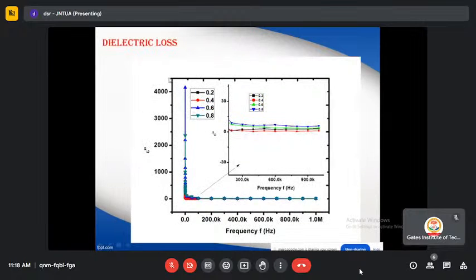Similarly, this is the plot between epsilon double dash and the frequency. The epsilon double dash values are also found to be 4575 and 2657 for the same compositions. In general, at smaller frequencies the grain boundaries become more active, whereas grains are more active at larger frequencies. This has been reported in literature. From this, we can say that grains exhibit a low resistivity, whereas grain boundaries exhibit high resistivity.